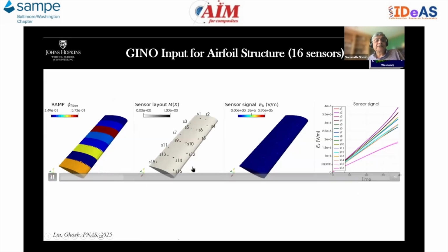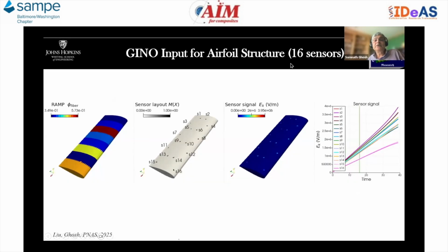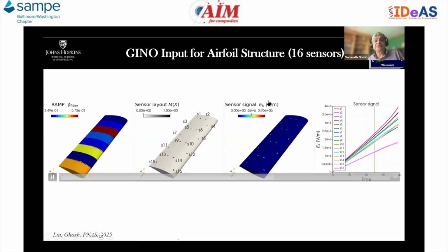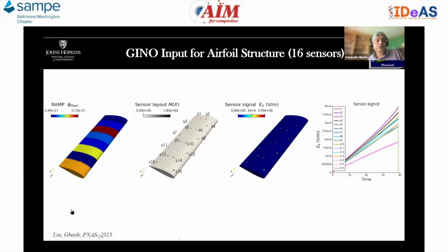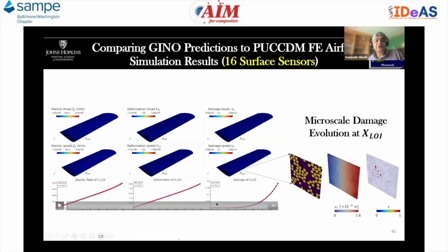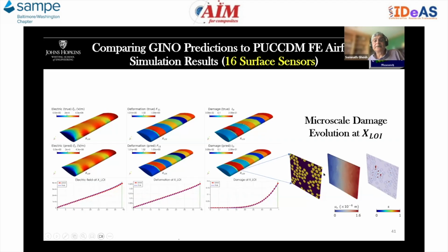If we move from a panel to a domain here, this is an airfoil structure with 16 sensors. This corresponds to the evolution of the electrical field at those sensors. And then corresponding to that, we have here the evolution of the electrical field, the deformation field, and the damage field, a comparison between the ground truth and the GINO predicted models.